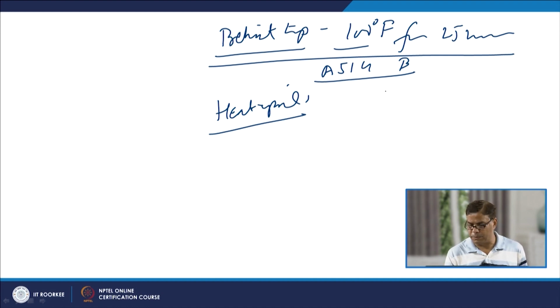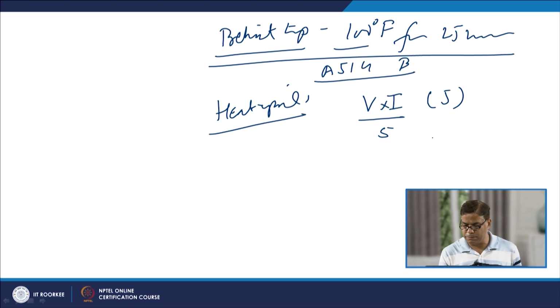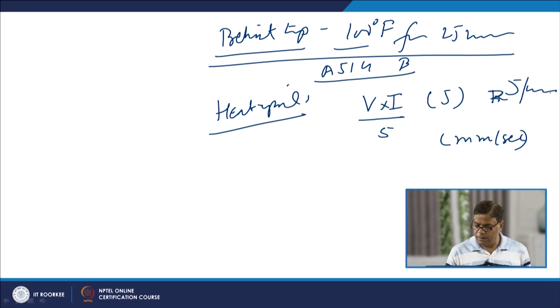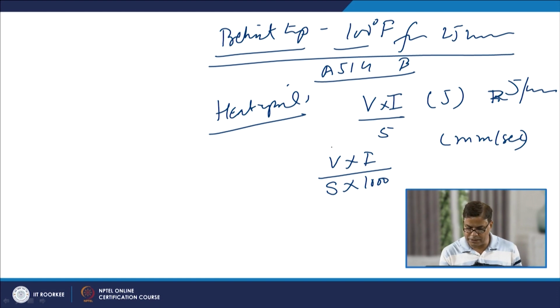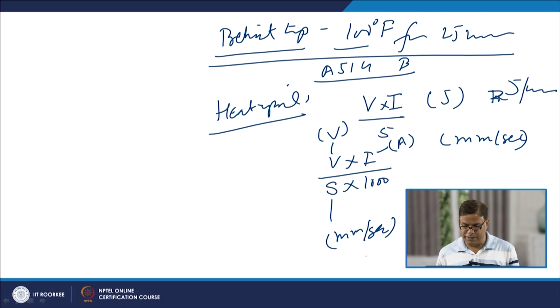Now, for all those arc welding processes, heat input is obtained through the voltage into current, gives us the power of arc in joule per second, and if we divide it with the welding speed, then we get the joule per net heat input. Normally the heat input is expressed in kilojoule per mm. So, we will be dividing V into I divided by welding speed divided by 1000. V is the arc voltage, I is the current in ampere, and S is the welding speed in mm per second. If it is in per minute, then we need to multiply 60.